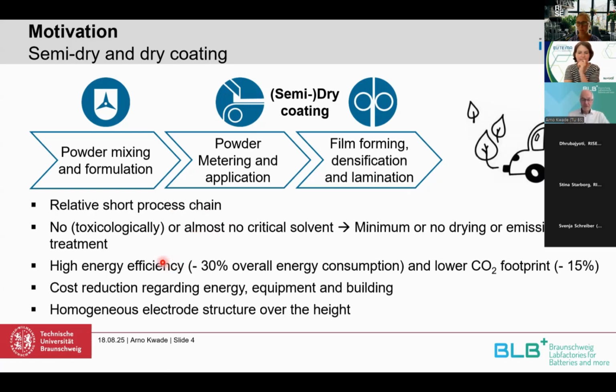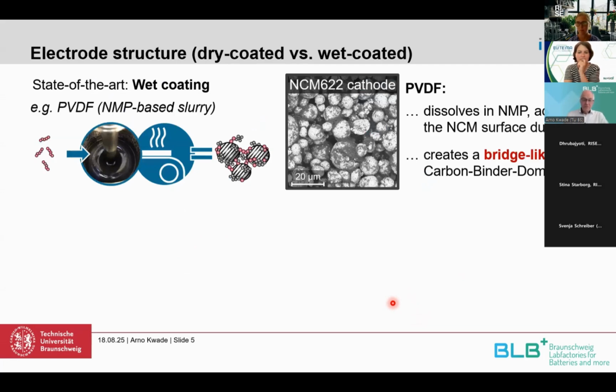We have a high energy efficiency, as already said. We can lower the CO2 footprint, and also overall we can lower the costs. Even, in most cases, we can increase the performance of the electrodes. And all that shows that it is really valuable to work in the direction of semi-dry and dry coating. But what do the electrodes look like if we change from wet to dry? So first of all, you see here the wet process, typical wet dispersing, and then coating and drying. And you see that we usually have the binder or the carbon binder domain as bridges between the particles, as we already also, for example, simulate that.